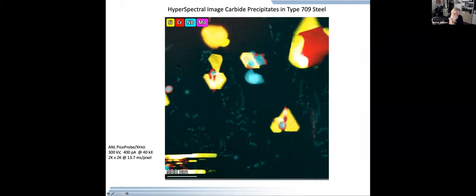Now, of course, this is a very large image, a 2K by 2K image. But if we zoom in on any one of these precipitates and look at the diffuse redistribution of elements around that, it's only taking less than seconds to do that analysis. So the ability of measuring very small concentrations, very small precipitates, is there.